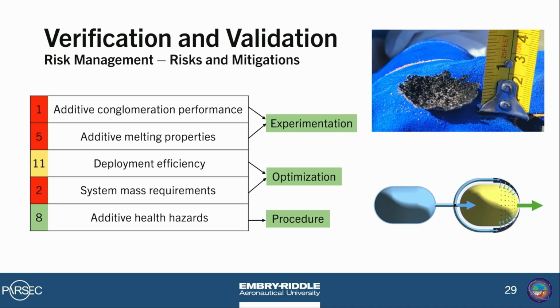However, we significantly mitigated these risks by coming up with successful experimental results. During testing, we have physical evidence of conglomeration, as Grant mentioned and as shown up there. So that mitigates the risk posed in the first risk and the first case of the second risk I had mentioned. Further testing will be needed to completely mitigate the risk of it melting too much.